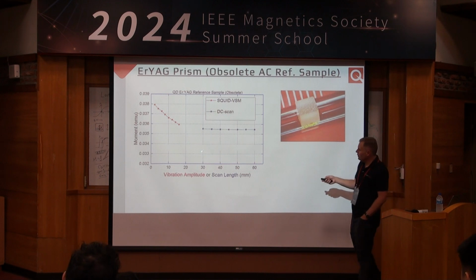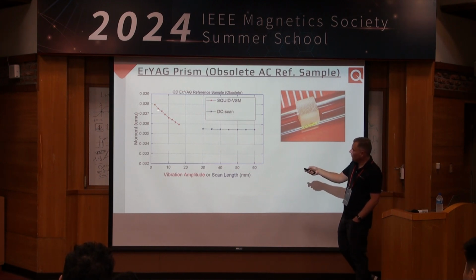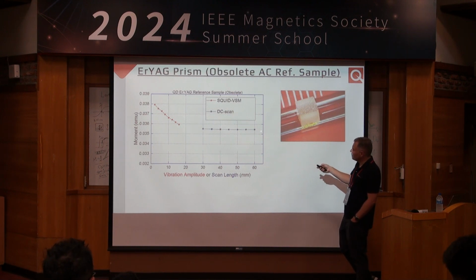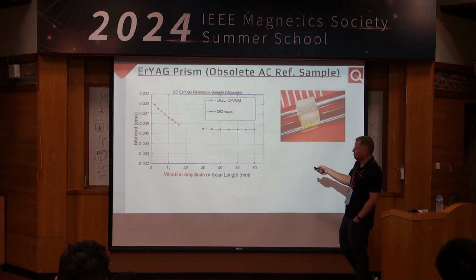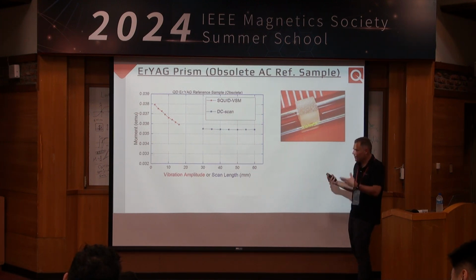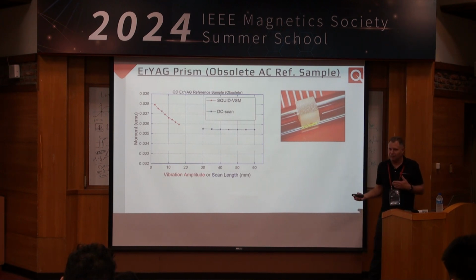And here's the moment as a function of vibration amplitude. Clearly it varies with the vibration amplitude. For the DC scan measurements, it doesn't vary much with the scan length here, but is this accurate? I don't know. We have to see what's going on here. But clearly there's something wrong here. The magnetic moment should not depend on the vibration amplitude. That does not make sense.